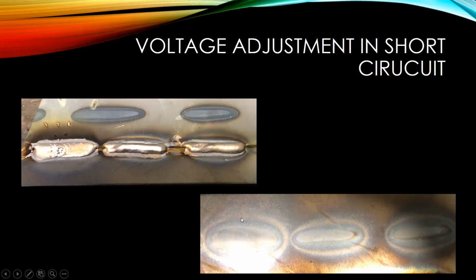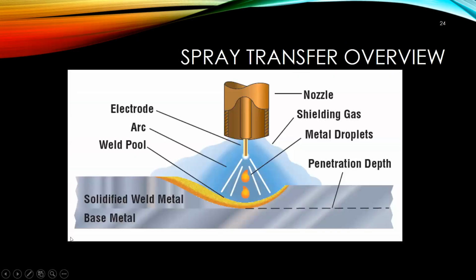And then looking at the bottom, this is the back side of that. Pretty normal amount of heat input. The first two were pretty close, and then you can see at that third one with all that extra voltage, it really affected that heat affected zone. You can see how much dark gray there is out here. So you want to make sure that you dial in those parameters for the joint and specifically for the car you're going to be working on.